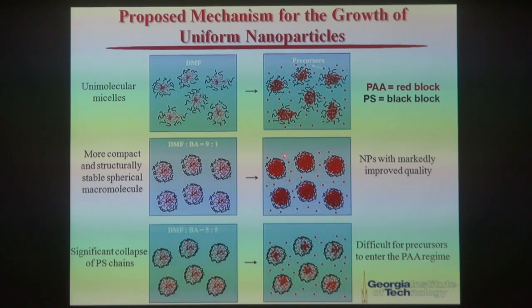At the same time, the loading of the precursors represented as the red dots into this well-defined compartment occupied by PAA chain increased, thereby leading to the formation of nanoparticles with markedly improved quality. Now, with the further addition of benzyl alcohol at DMF to benzyl alcohol 5:5 ratio, the outer polystyrene block now collapsed way too much because benzyl alcohol does not like PS, and PS does not like benzyl alcohol. So that make precursors having hard time to diffuse into the PAA regime to react, forming particles. Therefore, the regularity of the nanoparticle going down again.